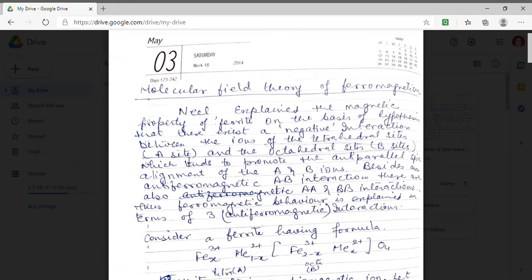A sublattice that means A site is a tetrahedral site and B site is an octahedral site. And there will be an interaction between these two sites that means there will be an anti-ferromagnetic A-B interaction.